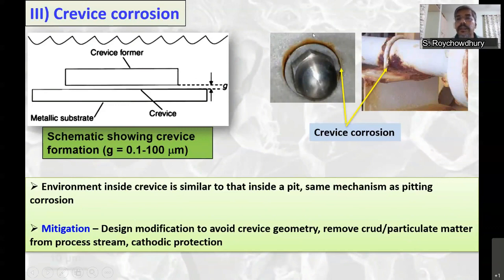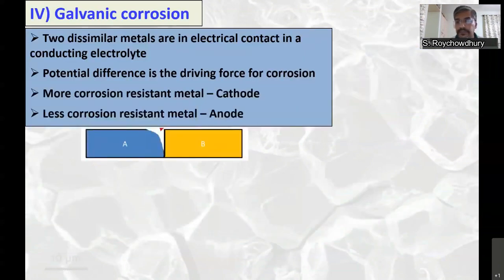Some typical images. So this is the washer. These are the preferred locations for crevice corrosion. So again, the tube support. Here also your crevice corrosion can occur. So mitigation is mainly by design modification. Avoid such crevice geometry. As I told before, weld instead of rivet. Remove crud or particulate matter, as they settle down and promote stagnancy and crevice formation. Cathodic protection can also help in preventing crevice corrosion.